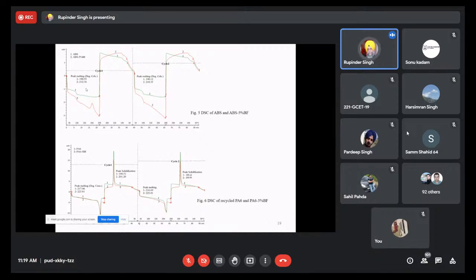And the fourth is the energy absorbed. These four things are typically of my interest as a material processing engineer. Now you can see in this case, once I was having ABS, it was taking the heat as 190. Once I add 5% banana fiber into it, the peak melting was increased. So that is really a good thing, that if I just add the agriculture waste into this, my peak melting is increased. And we tried to see it in the repeated cycle and we got a similar result.